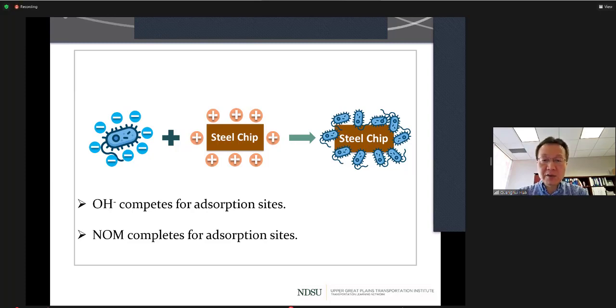And we know that steel chip surfaces have a lot of iron oxide. Iron oxide is positively charged. So because the charges on the E. coli and the steel chip surface are opposite, they tend to attract each other through electrostatic attraction. So that's the reason why steel chips are very efficient for E. coli removal.